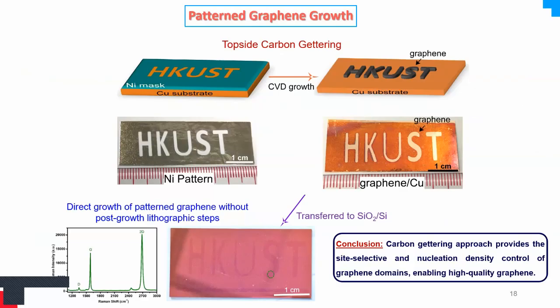Then we also used this method to pattern graphene. In this image, for example, you can see I put a nickel mask on which I have written something on top of it. This is my university name. After the growth, you can see over here on the copper, you have graphene only where you don't have the mask. Everywhere nickel is masking the copper foil, it will not let graphene grow. This is one of the very initial studies that I started with.